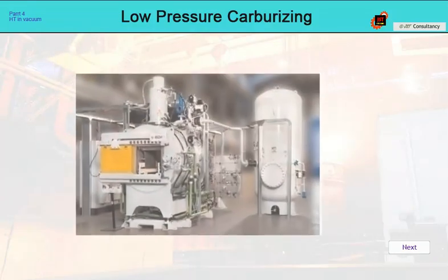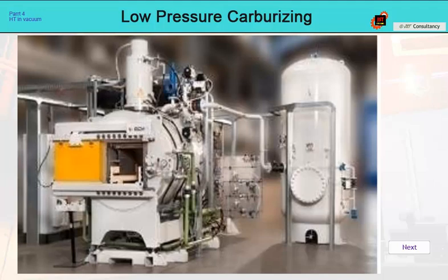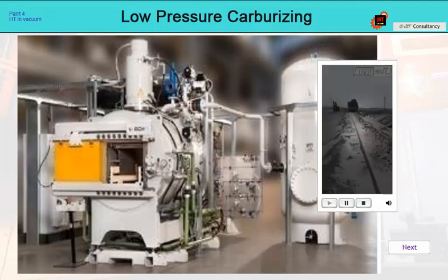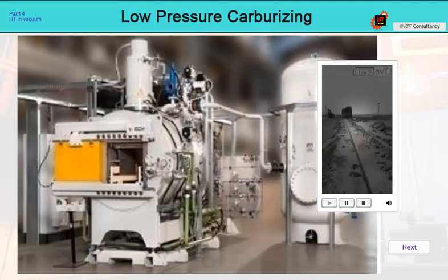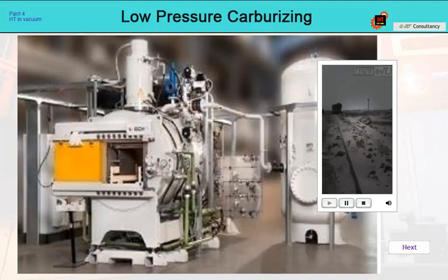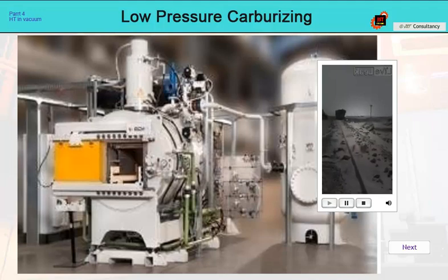Another safety issue is the purity and possible contamination of the oil with water. Due to exothermic reactions, water in the oil is a critical parameter and must not exceed 0.1%. The result can be interpreted according to the following video, which shows the reaction of hot slag in contact with a snowfield. Nothing like this can happen with low-pressure carburizing.